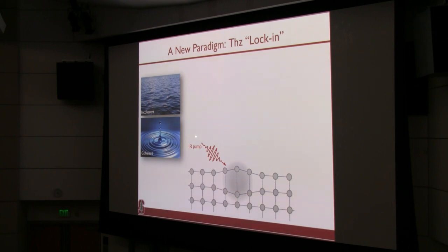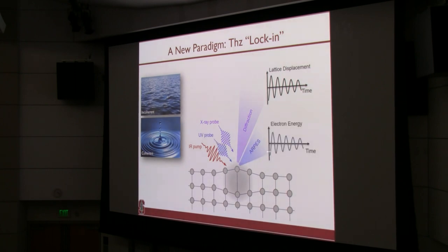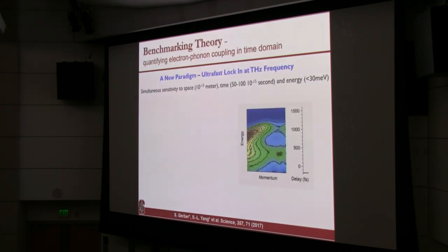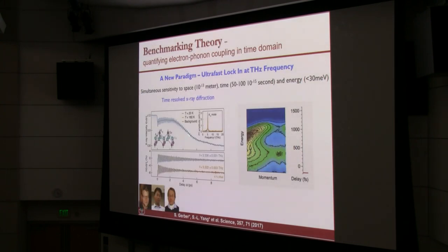And in this case, you have IR pump and X-ray diffraction to figure out if you were able to generate a coherent excitation, then you get a lattice constant. Then you can also use UV to probe and you get the energy level. And then you could get that. And that's the experiment.